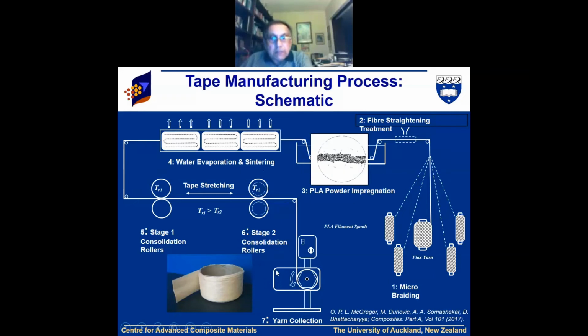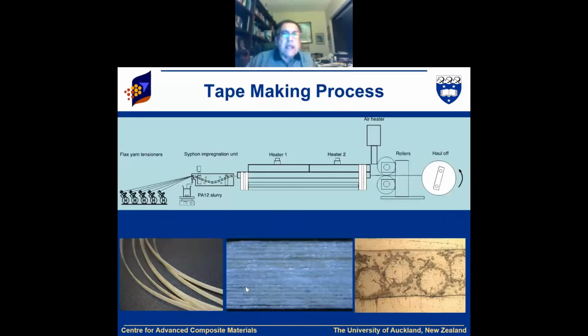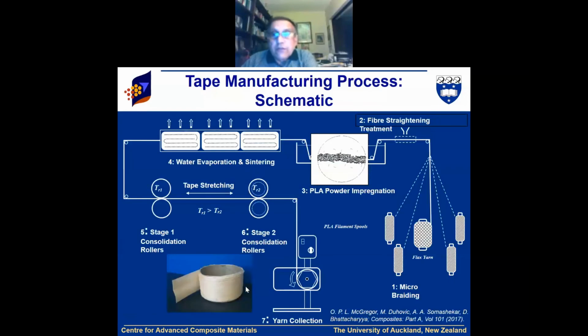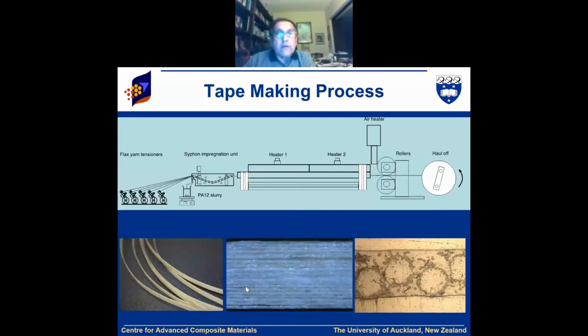And then you can stretch the tape, and that tape can be very long. It has got very good properties. And then we can use an automated computer controlled tape laying machine to manufacture products. So the student got some award and everything, and it was presented in New Zealand, also in California, to Germany, and a German company was interested in manufacturing polyamide rather than PLA, and we did manufacture for them, and they also wanted to increase the width. So initially we used 15 spindles. I'm not showing there, but for that German company we set it up with 30 different spindles, and we could manufacture very good products, and they were very happy.